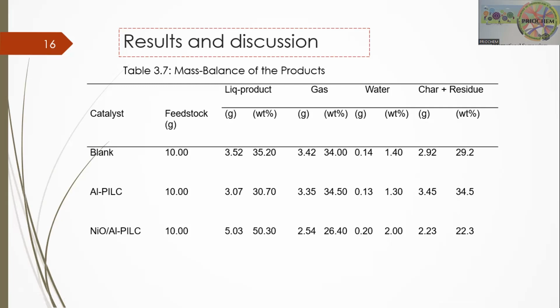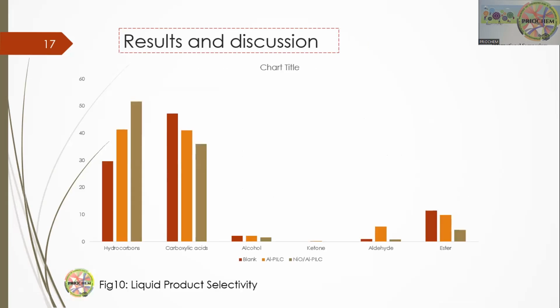But this is among the downsides of the deoxygenation, because we are using jatropha oil, which consists of many types of fatty acid. Irrespective, in some other cases, you use model compound. So the presence of char and the residue is due to the aromatization, polycondensation, and many other reactions alongside the deoxygenation reaction. So this is the liquid product selectivity for the hydrocarbons.